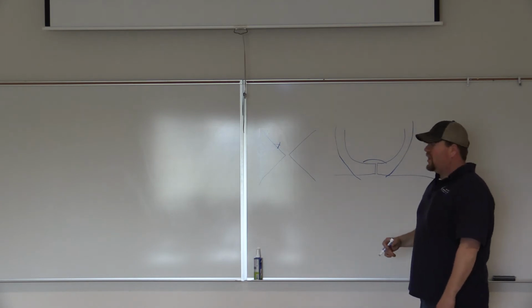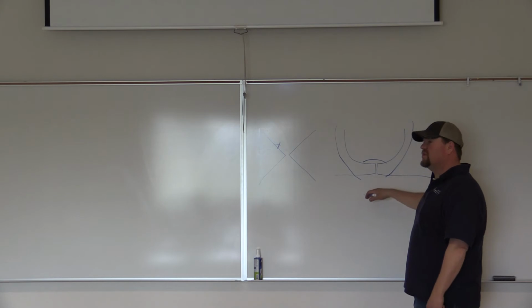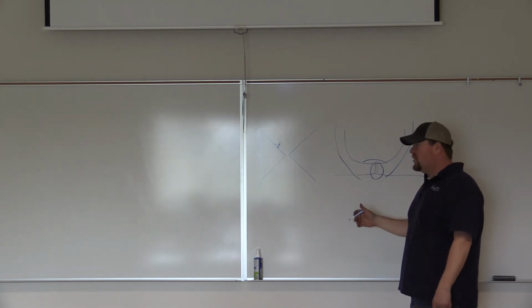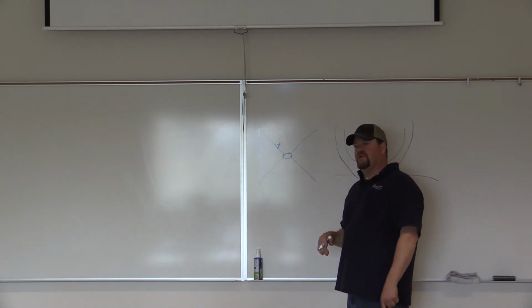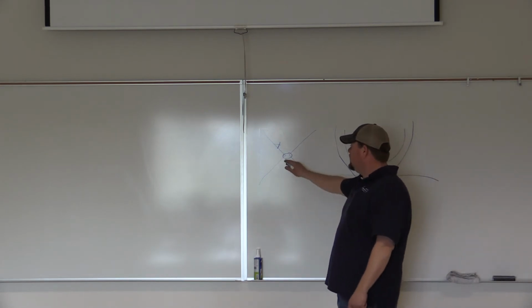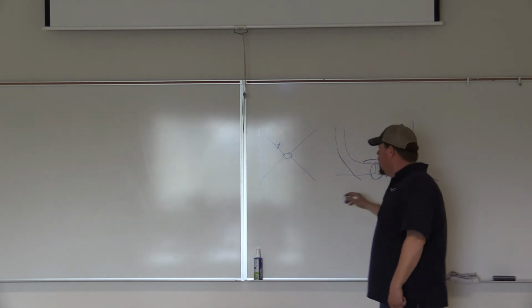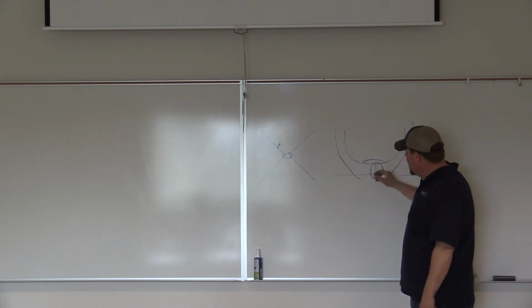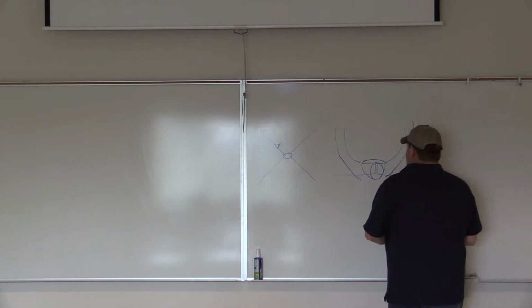And in electro slag welding and other situations, this might be a desired prep because you won't burn through. But 7018, in this case, you usually have to put this in with either a 6010 or a 7018. If you do a 7018, you're going to have to come behind it and grind it and back gouge it in. And a lot of times this was a one weld application. This might be an 1/8 inch thick, and they're asking for this root pass to be all in one first pass.